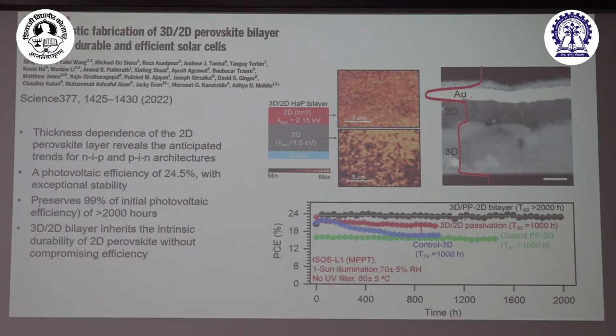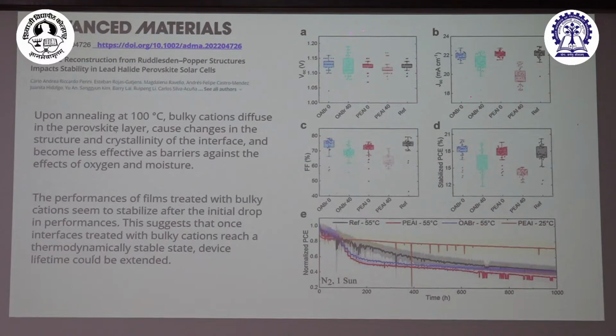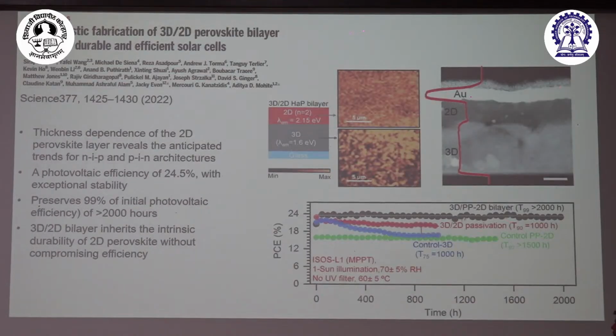Again, this is a published paper in Science, a very reputed journal, right? Then a little later, in Advanced Materials, there came another paper from Georgia Tech. And he says, upon annealing at 100 degrees, bulky cations diffuse in the perovskite layer, causing changes in the structure and crystallinity of the films. If you do it at room temperature, they're pretty fine, okay? This is PEAI at room temperature. There is a drop, but it's stable. But if you heat it up slightly, they start dropping down. Same system that this guy studied, right? So this is where the problem is.